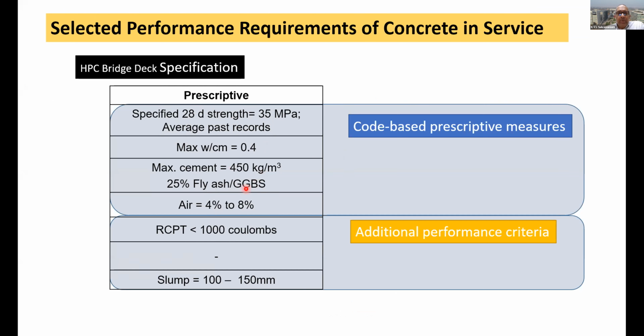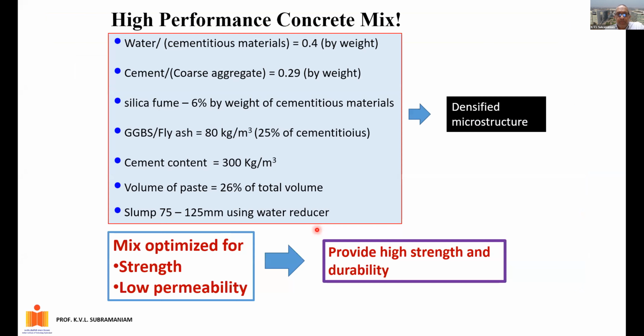With the use of ground granulated blast furnace slag, very low chloride penetration was achieved. This was a bridge deck which is exposed to de-icing salt. So basically de-icing salt used as calcium chloride. Chlorides would get through the concrete and the deck steel starts corroding. To prevent that, they produced concrete that was very densified, which had a very low RCPT, chloride penetration value.